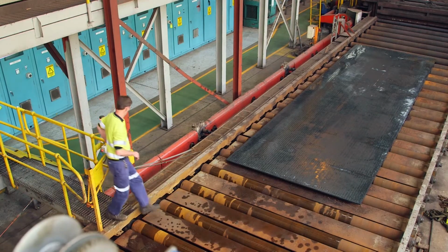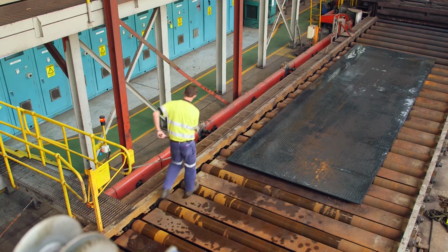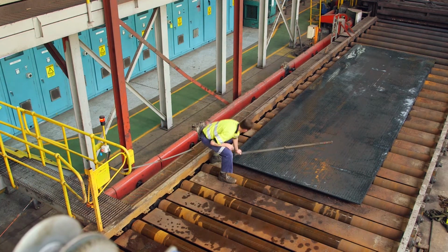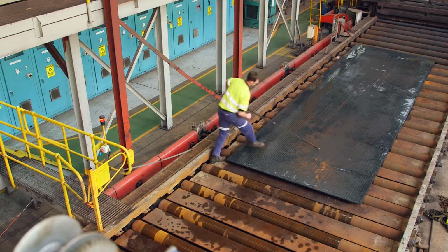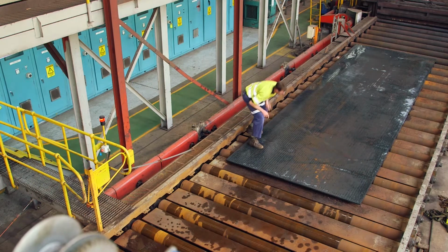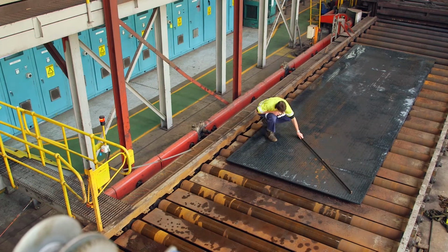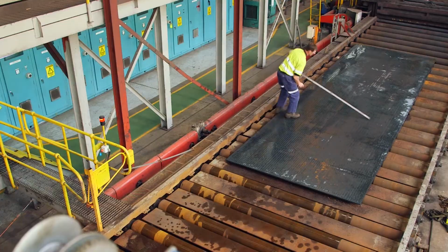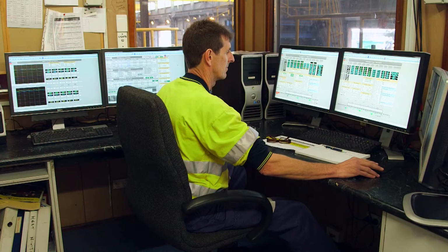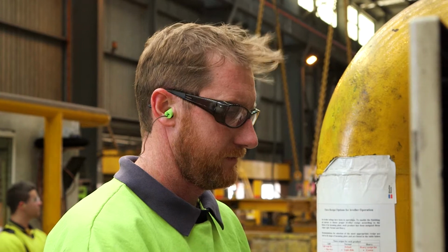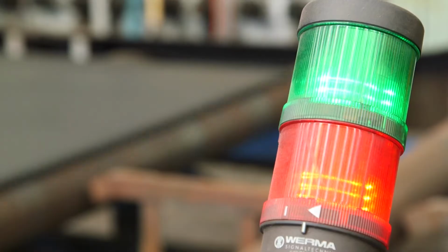Control tower operators are constantly monitoring the performance of the quench by inspecting plates immediately after quenching. This is done by using a 2 metre flatness gauge with 6 mm feet at either end. Depending on the assessed plate shape of the quench, the tower operator may modify the recipe to optimise the plate flatness obtained by quenching. After all heat treatment is completed, plates are shot blasted in a second shot blaster.